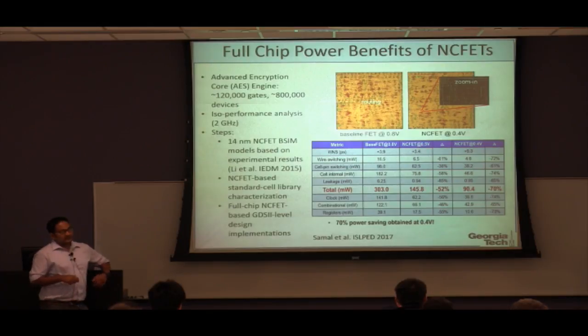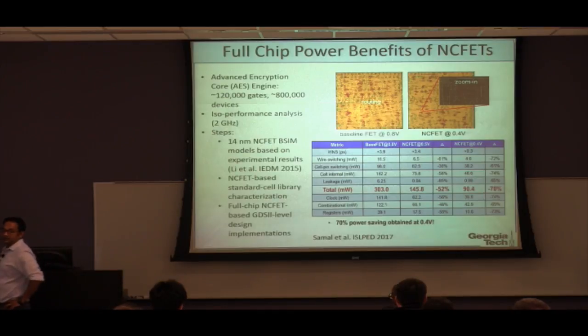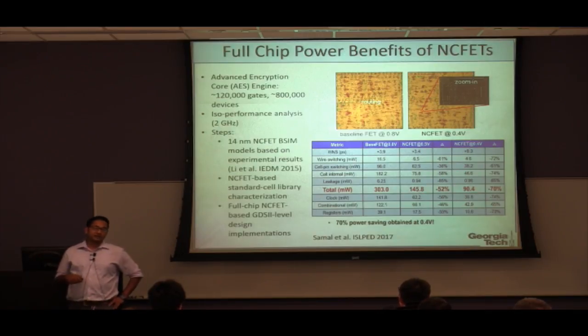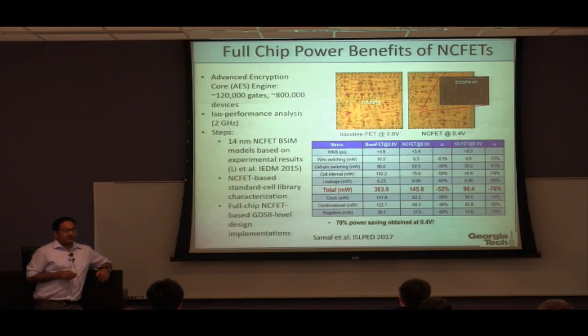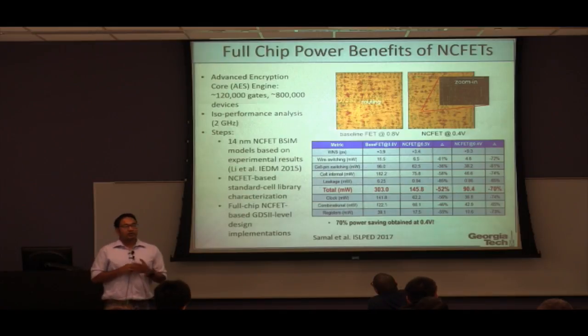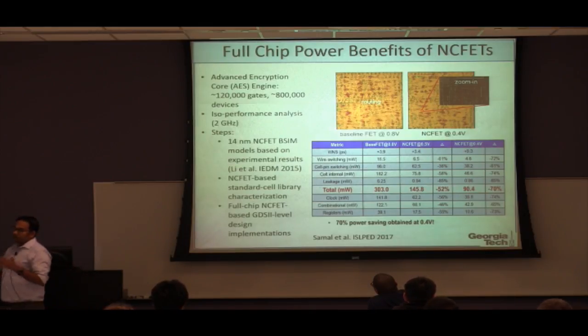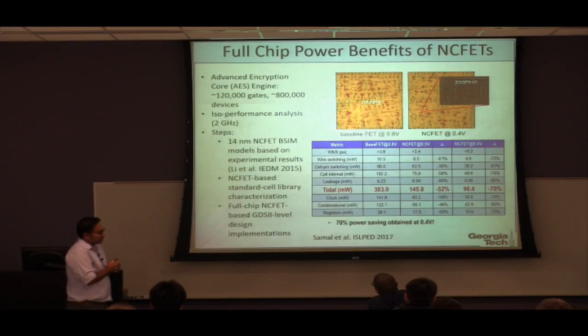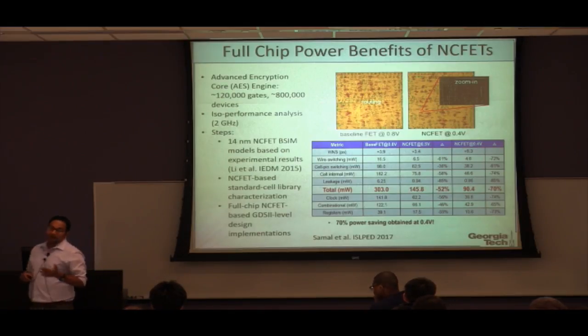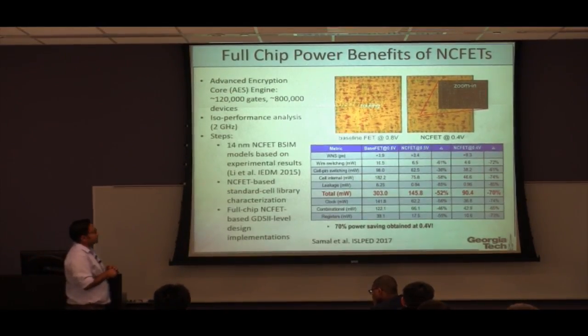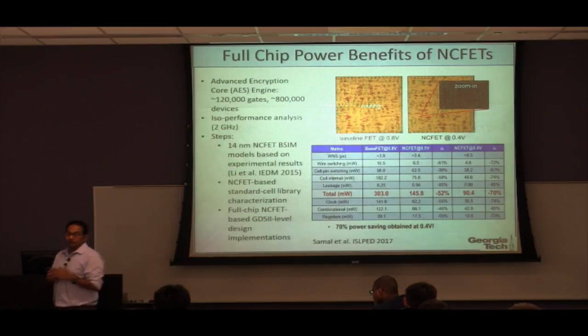Now, for the same performance at 2 gigahertz, we need only 0.4 volts in a negative capacitance transistor technology. And when we run the negative capacitance transistor chip at 0.4 volts at 2 gigahertz, it actually requires 70% less amount of energy compared to a baseline technology where you do not have negative capacitance. So again, all told, these are simulation results, but this really gives us an indication that if we can use this phenomenon properly, then this could lead to significant power benefits in electronics.